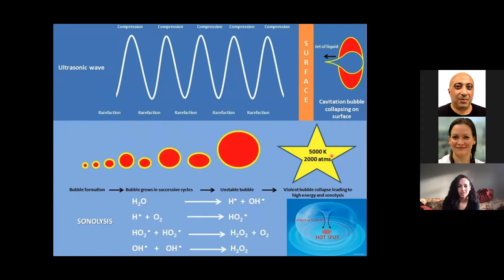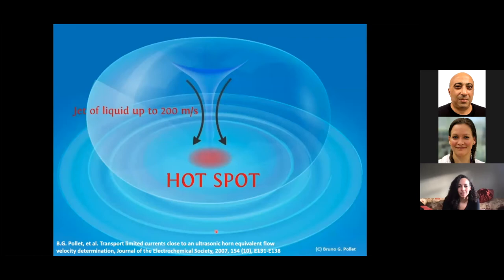So this is your physical effect. You will have your surface being eroded. But you also have the chemical effects, called sonolysis, or water sonolysis. You are splitting your water molecule into radicals, hydrogen radicals and hydroxyl radicals. And by recombination, you produce hydrogen peroxide. This is one of the papers that showed, by the use of electrochemistry, that you could reach jets of liquid of 200 meters per second. And the hotspot is where you get most of your energy focused in one area.